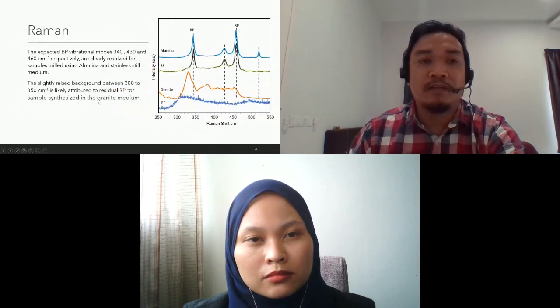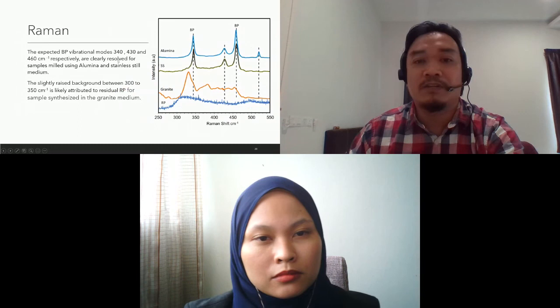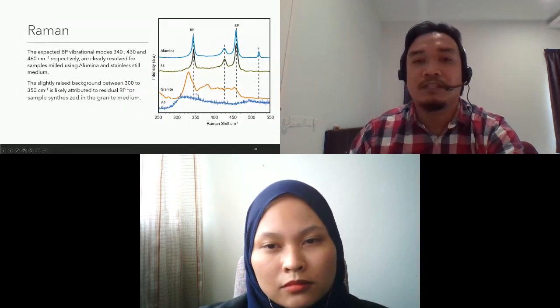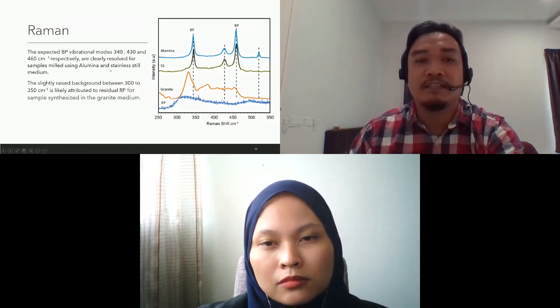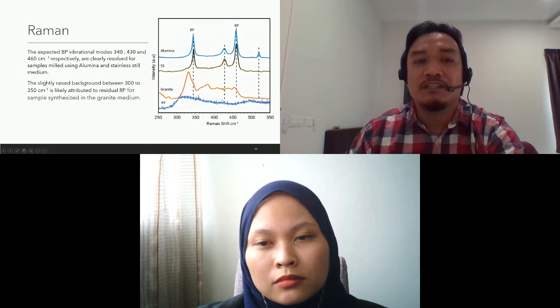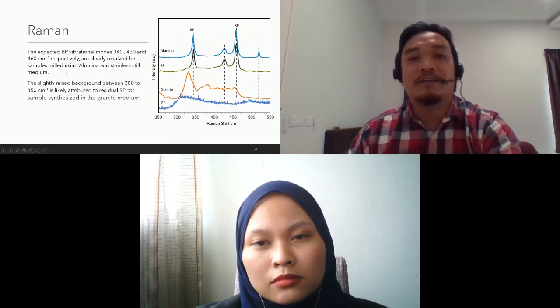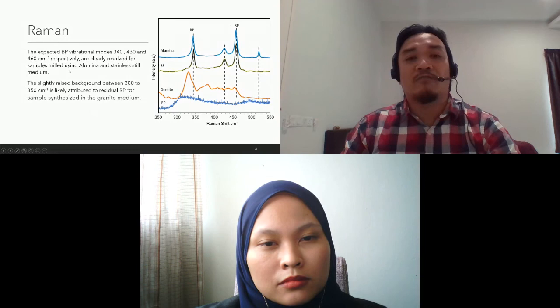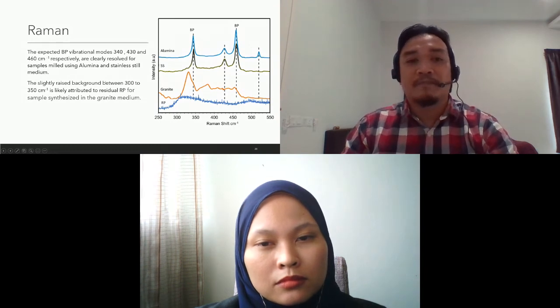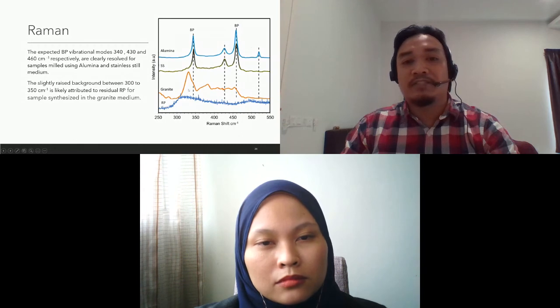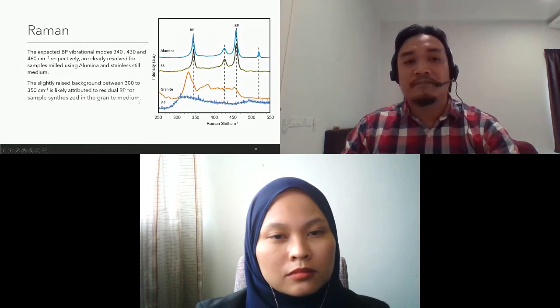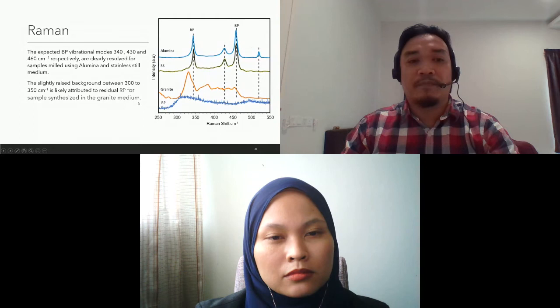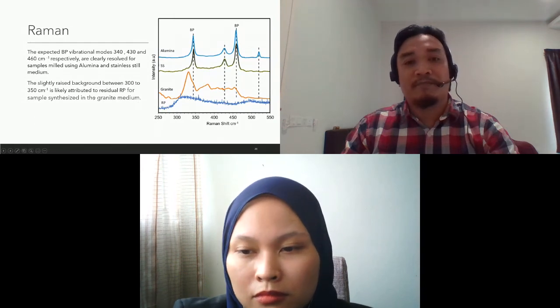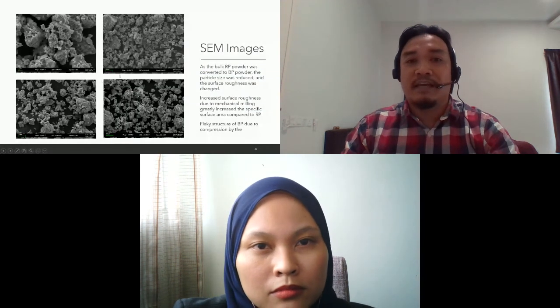And also the Raman, the expected BP vibrational modes at 340, 430, and 460 respectively, are clearly resolved for samples milled using alumina and stainless steel medium. The slightly raised background around 300 for granite is attributed to residual RP in the sample synthesized in granite medium. Okay, this is the SEM image.